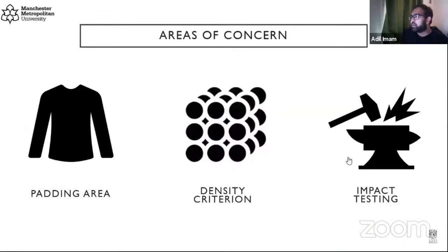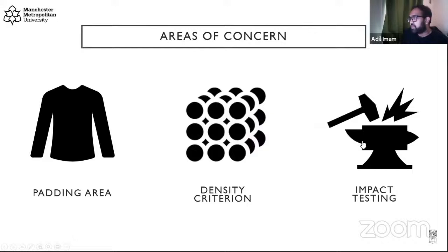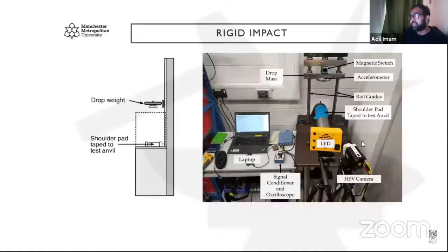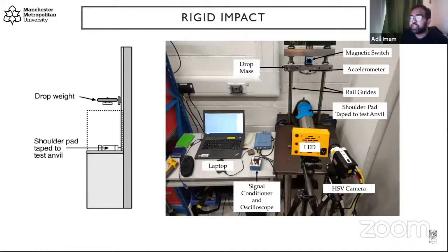So beyond that, the third thing we found that was a concern was the impact testing. Now, the impact test set up in the regulation defines a steel plate dropping onto a steel anvil, and you place the padding in the middle to check if it does not offer too much protection. Now, it is not, you'd never find a steel on steel impact during a rugby game. So it is a little bit unrealistic. It is repeatable, but unrealistic.